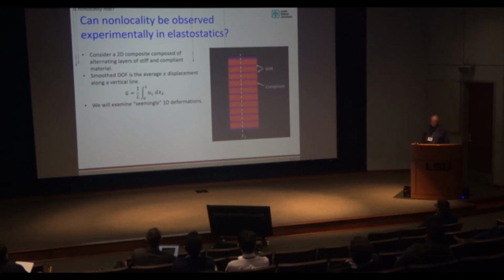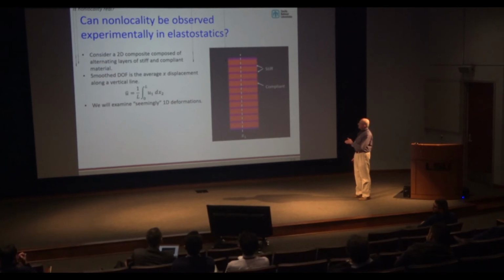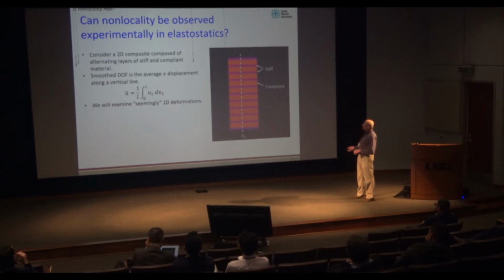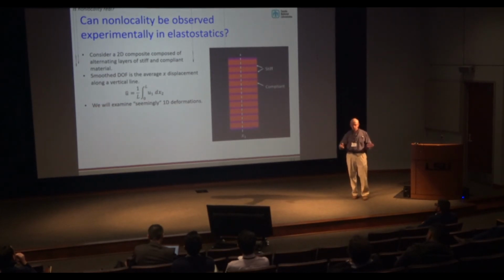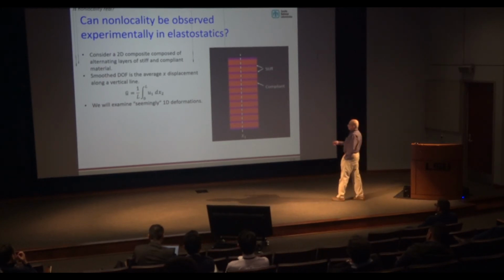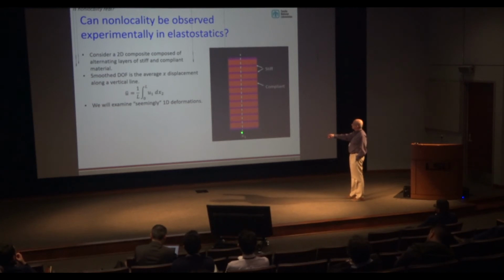Well, so much for that 1D example. This is another example in 2D, which demonstrates a different aspect of using homogenized degrees of freedom. So this is a 2D composite with alternating layers of stiff and compliant elastic materials. And we're going to look at 1D type deformations. We're going to compress this from the vertical boundaries and see what happens. Our homogenized displacements are just a volume weighted average along vertical lines.